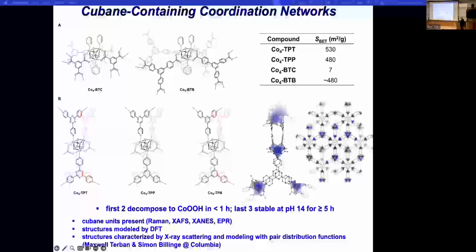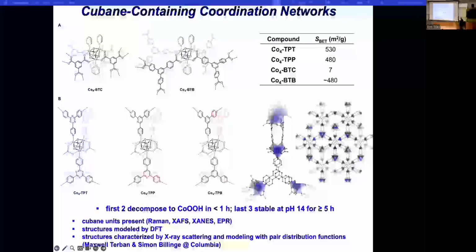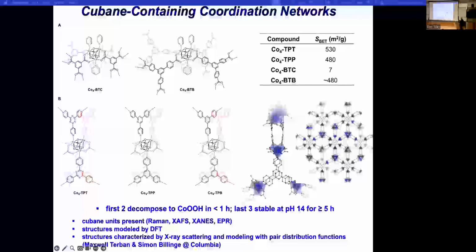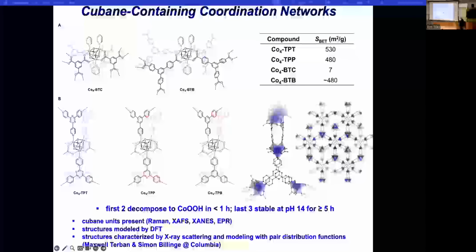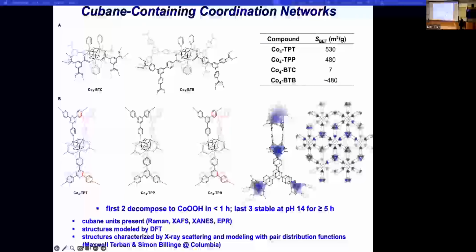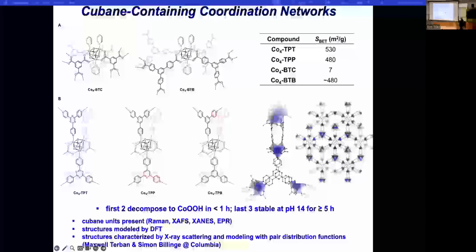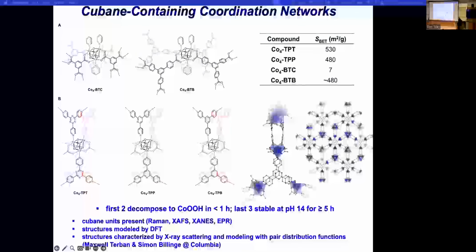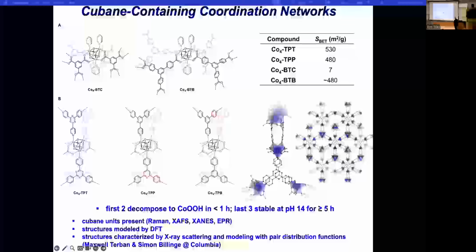And in terms of structure determination, we were helped by PDF studies in the group of Simon Billinge at Columbia, and DFT studies as well. We can tell that the cubane is present from Raman spectroscopy and X-ray techniques, EPR. And the bottom line is that cubanes in these networks behave very much like they do in solution.